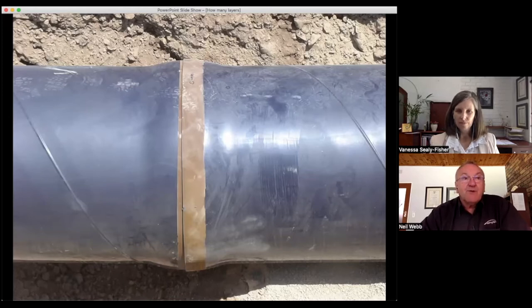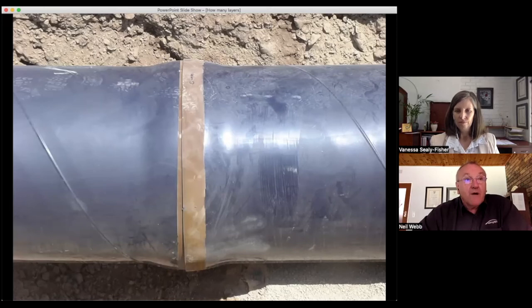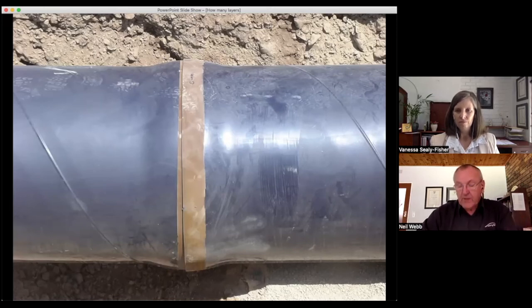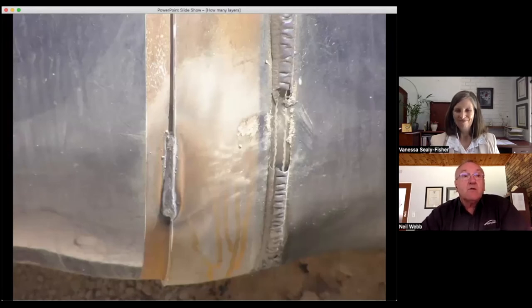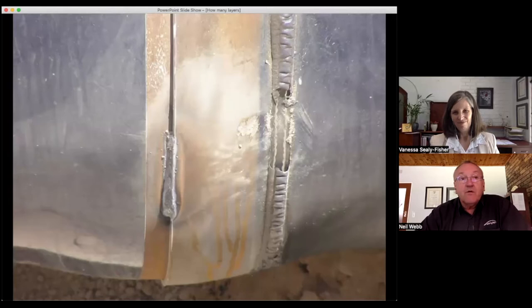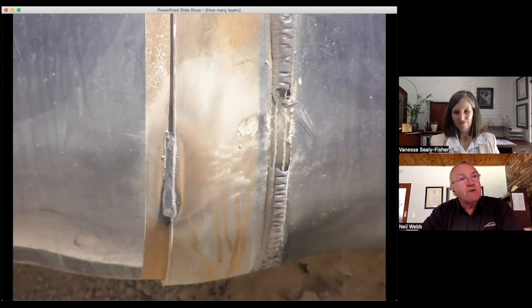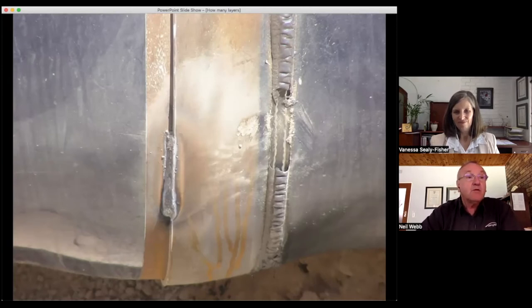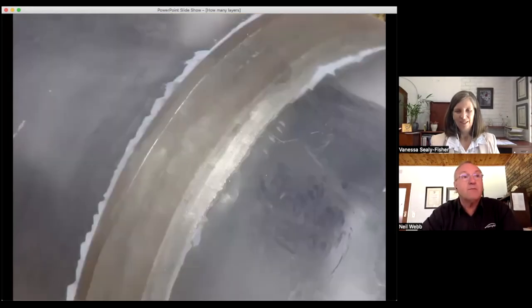The pipe gets welded on the inside, which naturally burns the external coating, as you can see. The external double bell is reinforced with spigot welding, and the polyurethane is used to seal the crevice formed between the inner and outer bells. One advantage of polyurethane is that it has gap-filling properties.